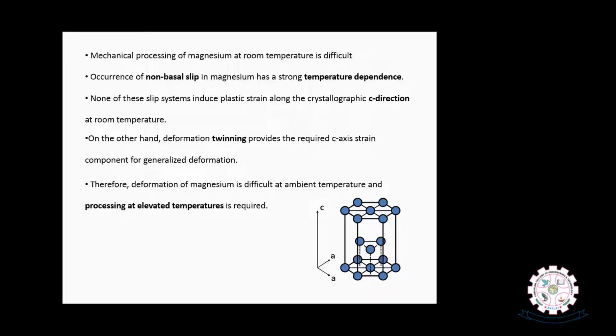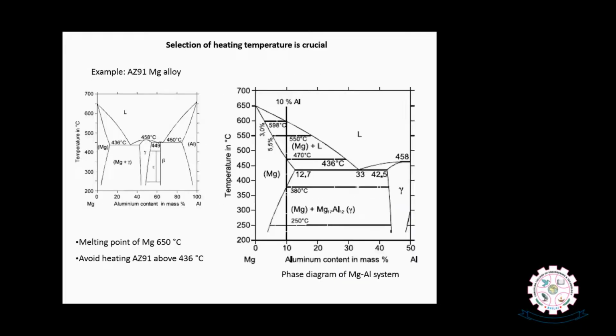On the other hand, deformation by twinning also helps to aid plastic deformation of magnesium. Therefore, we see in microstructures of most magnesium and magnesium alloys the presence of a number of twins. Therefore, deformation of magnesium is difficult at ambient temperatures and processing at elevated temperatures is required. So when we see the magnesium alloy phase diagrams, for example AZ91 magnesium alloy, we should decide the temperature at which we should deform the magnesium alloys. We should adopt the deformation processes at different temperatures.